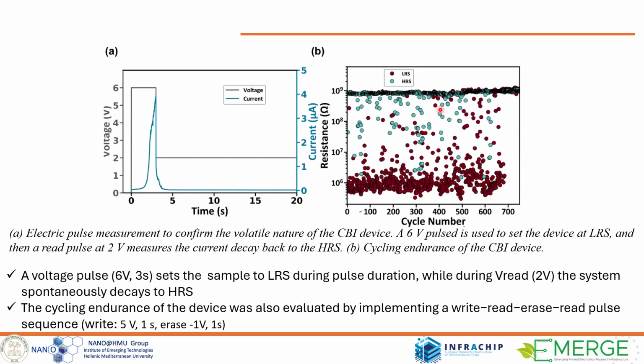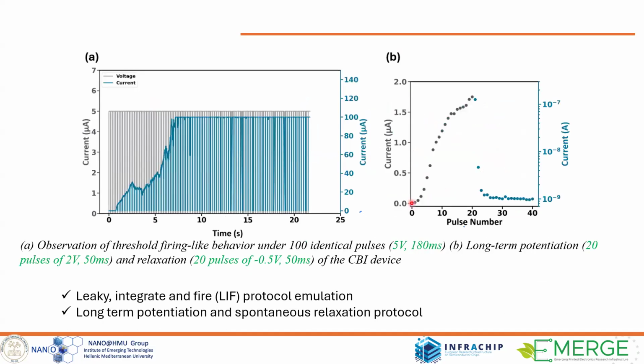A typical cycling endurance curve is shown here on the right, at least 700 cycles with a good transition between high and low resistance.